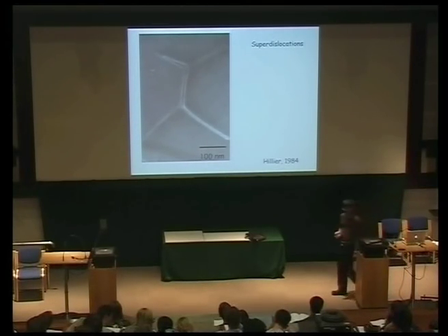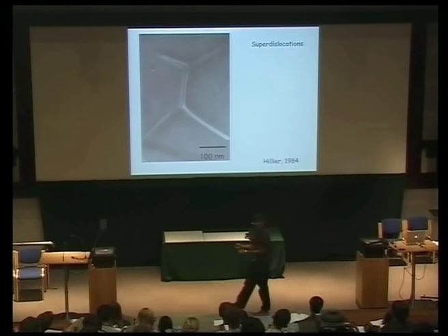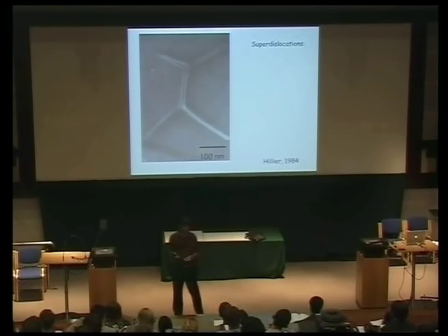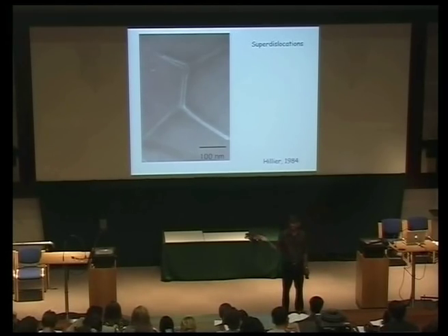This is the dislocation structure. You can see there are pairs of dislocations inside the gamma prime. And in between, you have the antiphase domain boundary, where you have disrupted the order. So instead of seeing single dislocations with a Burgers vector of a/2 <110>, you actually see pairs of dislocations when you look using a transmission electron microscope, inside the gamma prime. Incidentally, this also applies to the aluminium-lithium alloys that we did in the last lecture, because it's an analogous system. You have Al3Li in a disordered matrix of AlLi.